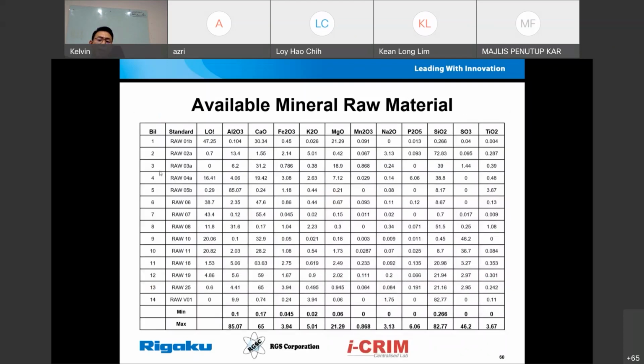And this is the available mineral raw material standard, and this is the concentration range they cover. So if your sample is roughly within this kind of range, it can be done. The good thing about UKM i-CRIM is that they also have a fusion machine. Even if you give them the raw material in powder form, they can make it into a fusion bead, and subsequently use this calibration curve to measure your sample.